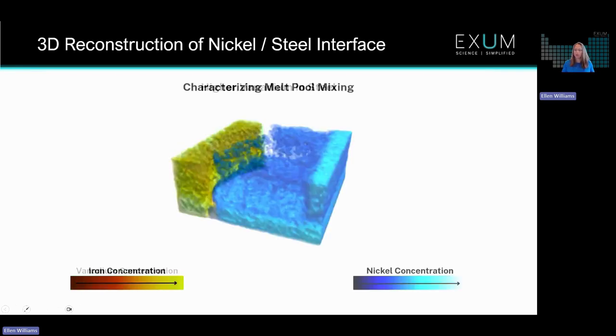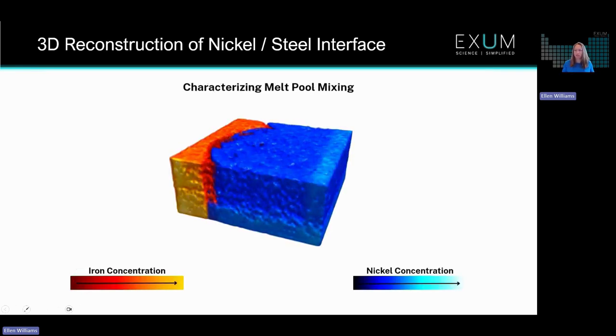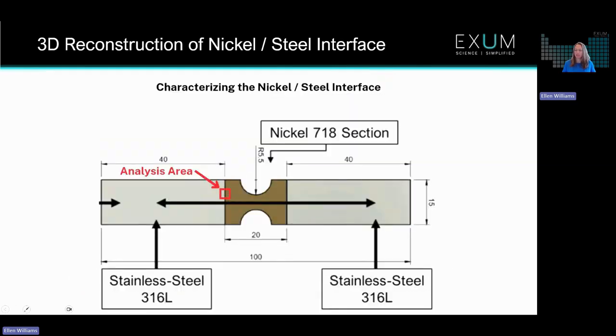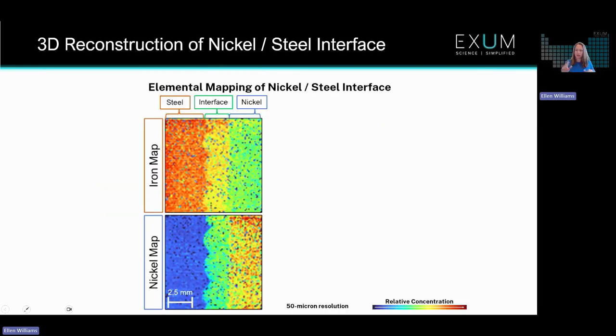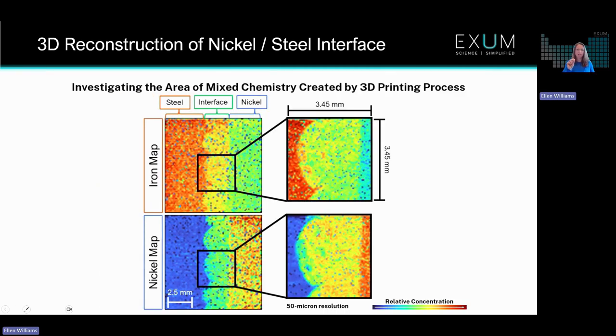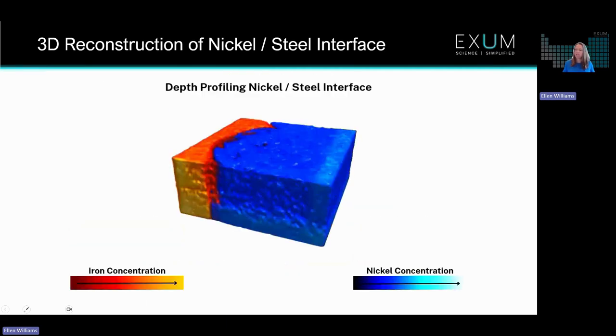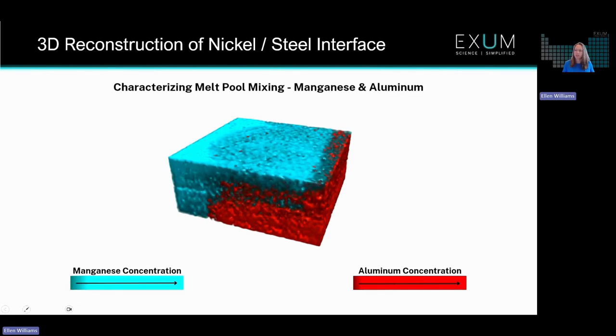So now that I've oriented you on the video, I am going to let it play again so that we can look at some of those elements in a little bit more detail. So once again, we took the tensile bar sample and analyzed the 316L to Inconel 718 interface. From an elemental map, we were able to determine exactly where we should analyze in order to profile through one of those melt pool beads. By doing 20 layers of analysis, we corroborated with a microscope that we removed about 10 microns of material. And now we can look at all of these different elements.